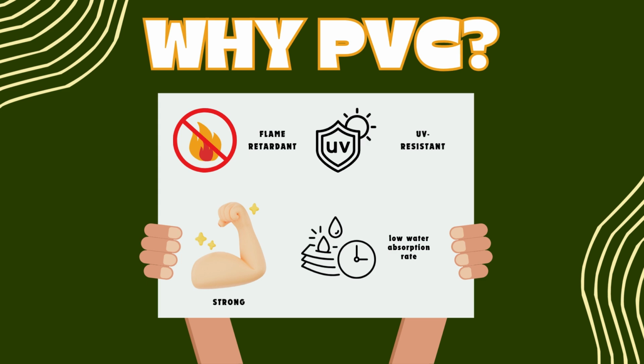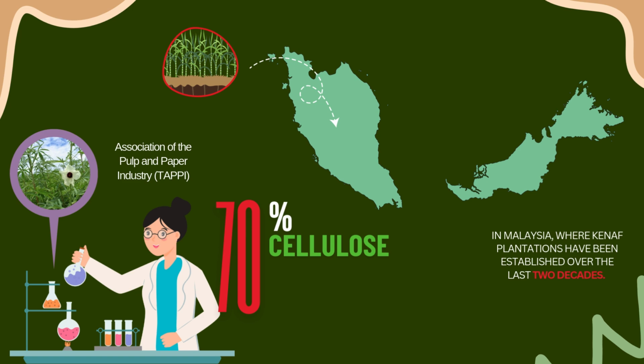Why PVC? Because it's strong, UV-resistant, fire-retardant, and has a low water absorption rate. These qualities make it an ideal material, especially in regions like ours where floods are a recurring issue. Malaysia has a significant amount of Kenaf plantation, and Kenaf is a fast-growing plant with exceptional fiber quality, making it an ideal candidate for reinforcing recycled plastics. In our study, Kenaf fibers were tested according to the Technical Association of the Pulp and Paper Industry (TAPPI) standards and were found to contain over 70% cellulose, which directly contributes to the strength and durability of the final composite